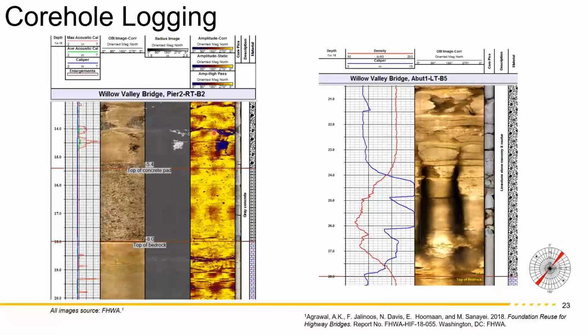Here you have to have the core hole filled with water and use ultrasonic waves in kind of a sonar, and then you can get reflection back from the walls, so you can look at it ultrasonically this way. Now, if you see any vugs or issues in here, you can find what the depth is, kind of like a sonar, as is shown here.